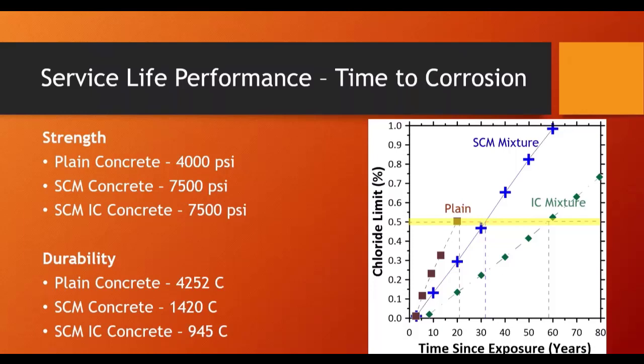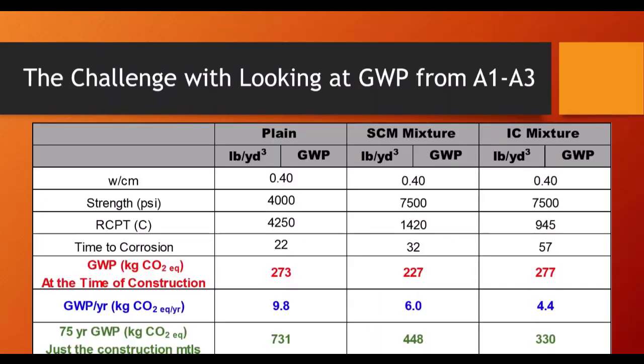So now all of a sudden, this starts to impact our thought process because we've changed the compressive strength by taking some cement out and putting some slag in. We've also changed the RCPT values here pretty substantially, and we've done more sophisticated service life modeling where we've shown those times to corrosion. And all of a sudden now, we can start looking at this global warming potential in different ways. And one of the arguments that I'm going to make is a challenge with the way we're looking at the GWP right now is we're entirely focused on A1 to A3, cradle to gate.